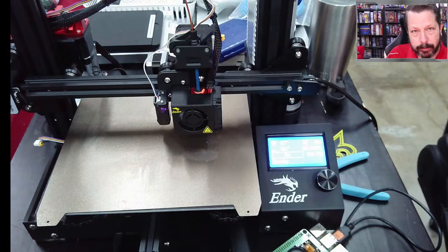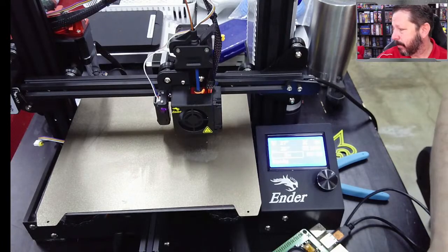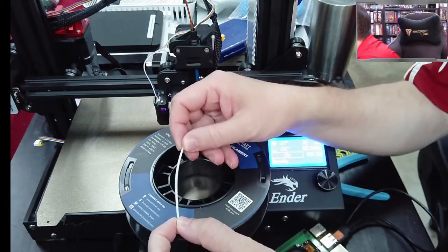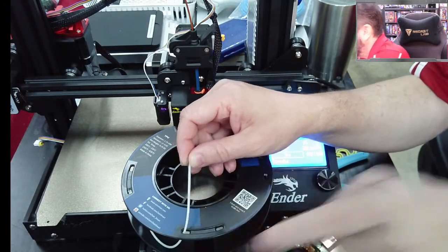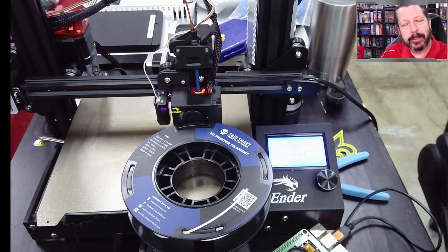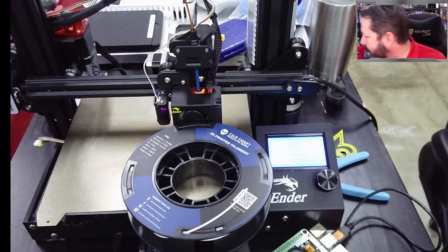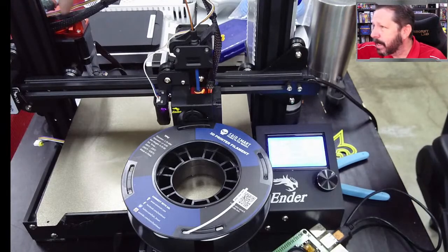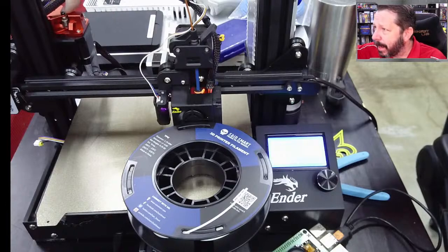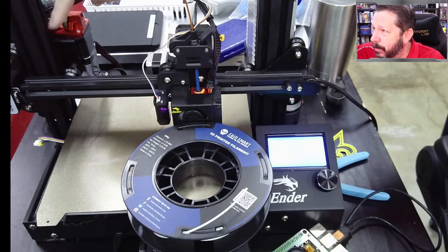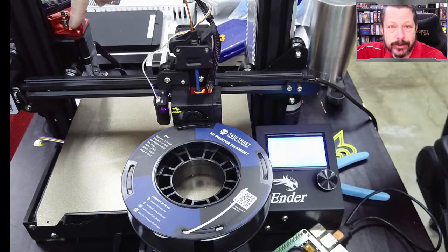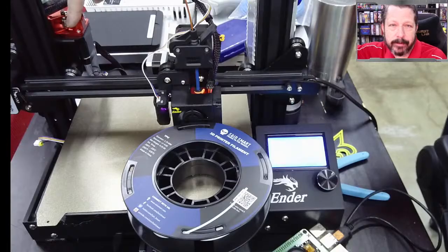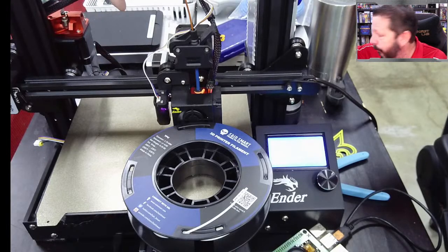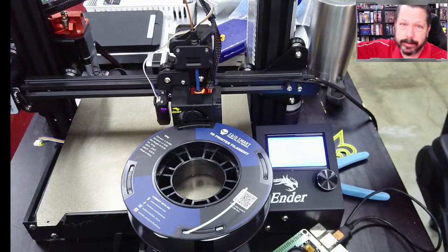The problem with the long filament path is that as this TPU gets more and more flexible, you have to push it into the tube, and it wants to buckle, and so it buckles all inside that tube, and it can give you a lot of little friction points in there, and it can jam. Another thing that can happen that is annoying but a little bit interesting is on this kind of feeder back here, if you go too fast, like feeding the print too fast, it'll actually start coming out the side, and you'll have this big loop of filament just coming out of the side because it's unconstrained here. And these kind of feeders rely on the rigidity of the filament itself to keep it moving forward versus just coming out the side over here and not printing at all.